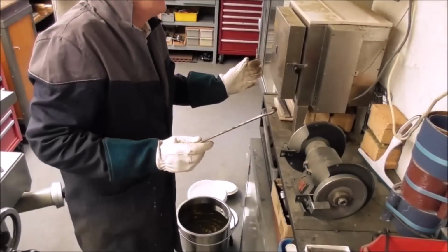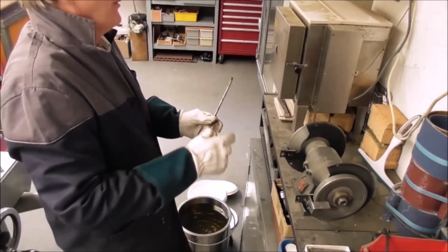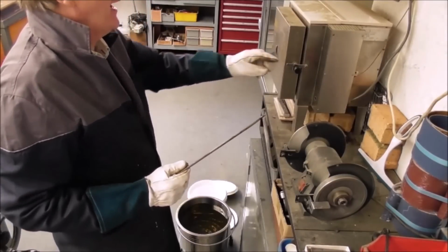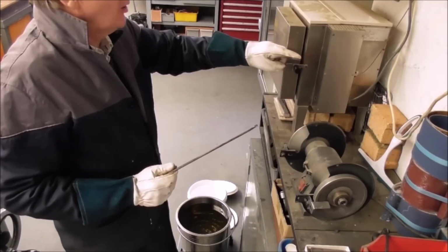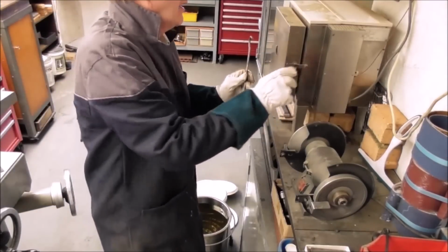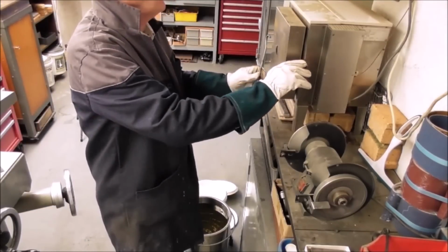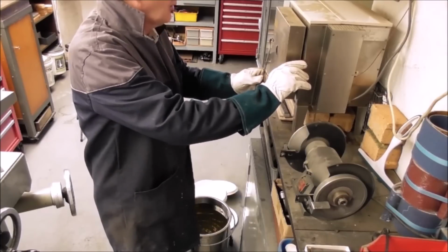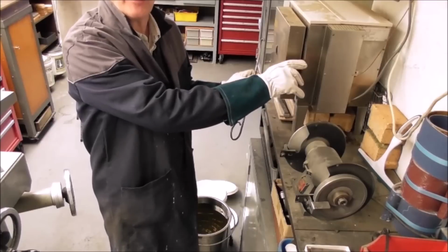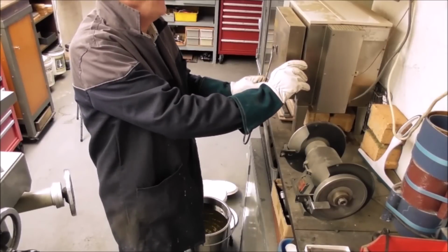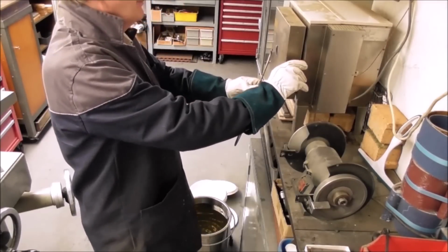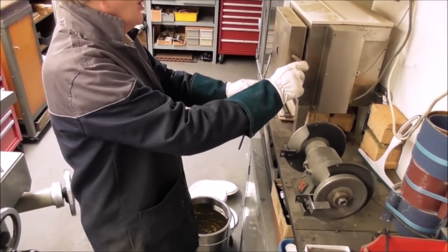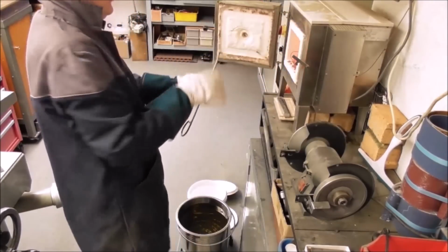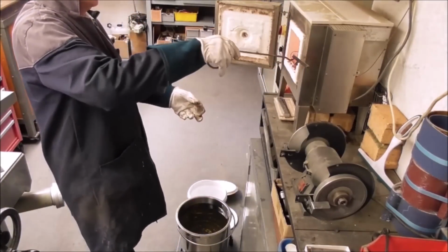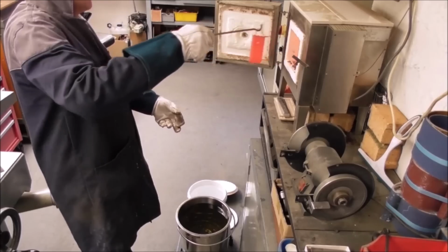Well, it's been at 800 degrees now for half an hour, so that should have soaked into the bigger part. Not at all influenced by the fact that I have to drop Jan down at the garage. And I'm going to quench the bigger part in oil because it doesn't need to be glass hard, and then quench the smaller parts in brine. Oh, maybe I'll test it for hardness first. Alright, let's go. Don't fumble it.